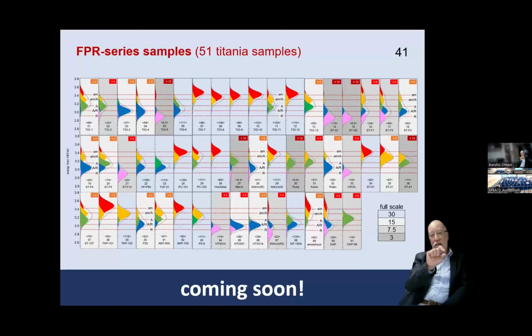So for small anatase particles, the inside might be anatase crystalline, but that is completely covered with amorphous. And you cannot see the violet-only patterns. That means there is no sample exposing only the rutile surface. All these rutile samples contain other parts, not only rutile surface. And also there are almost no anatase-surface-only samples. The bottom right one, the green one, is a laboratory-made sample. And almost all surfaces are covered with anatase, and that is an octahedral particle.